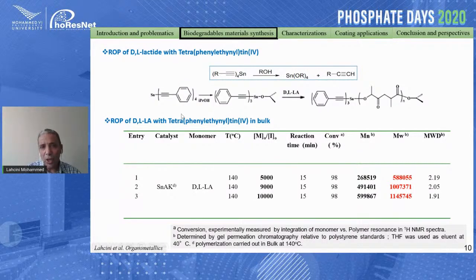But what I would like to show you in this table is that we used this catalyst without any solvent, in bulk condition at high temperature, the same temperature as in the industrial preparation of polylactide, with really high ratios: 10,000 to 1, 9,000 to 1, and 5,000 to 1. We observed really high molecular weight, and total conversion was achieved after 15 minutes. It was the first example in the literature in which we can prepare polylactide with a catalyst in open air, because with all other catalysts we have to work under argon, nitrogen or vacuum.